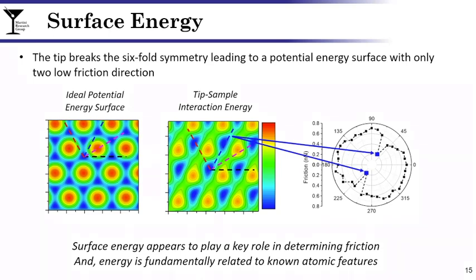However, recall that I told you that friction is not just one material, it's two things sliding relative to one another. So we recalculated the potential energy surface using the model tip in the simulation and found a very different story. Specifically, we found that the tip breaks the 6-fold symmetry, and that leads to 2 directions of low energy corresponding to our 2 directions of low friction. So it seems here that surface energy, again, something fundamental about the material, plays a very important role and potentially is a link between friction and the atomic nature of the materials.